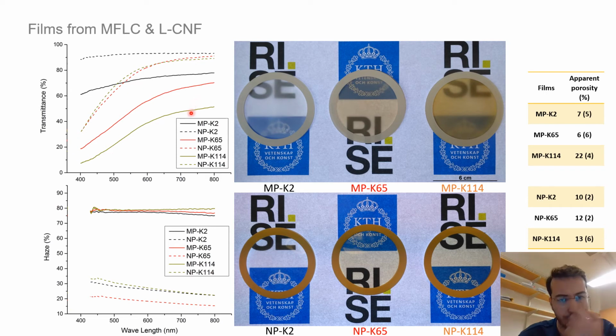And in the films with higher kappa number or higher lignin, we see that the transmittance is less. This is because of presence of chromophores in the lignin, and especially in the lower wavelengths, which is a characteristic of lignin to absorb light at lower wavelengths, blue light region, for instance.